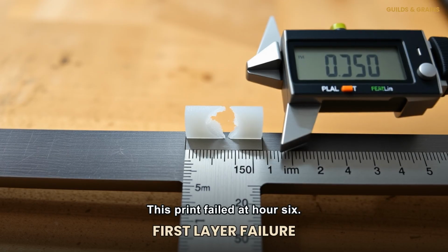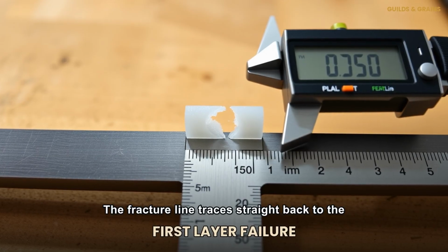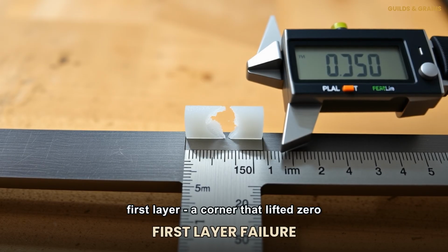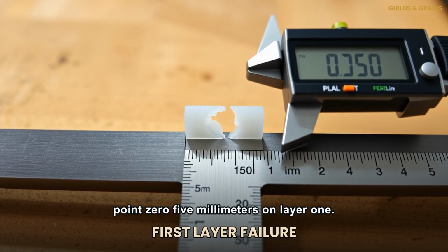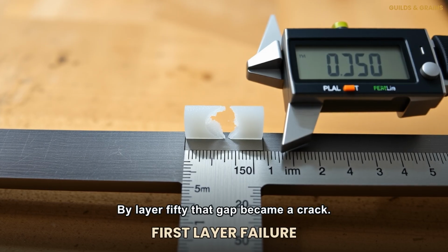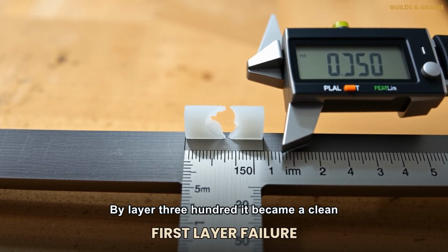This print failed at hour 6. The fracture line traces straight back to the first layer, a corner that lifted 0.05 millimeters on layer 1. By layer 50, that gap became a crack. By layer 300, it became a clean break.